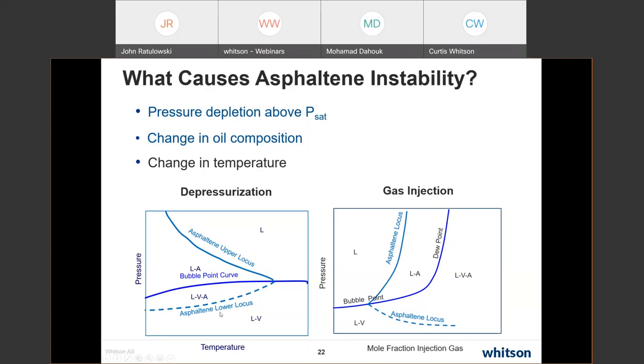Change in oil composition is specifically important in gas injection processes. You can see this phase diagram over here, which is similar to the sorts of phase diagrams we see with CO2 injection. You can see as I continue to add CO2 at some point here above the bubble point, I will have a region where I have the liquid phase, the oil phase, and asphaltenes precipitated. And again, as I go down below the bubble point, I'm releasing gas from the system. So I'm actually increasing the solubility of the asphaltene, and eventually it will go back in, maybe. So I have an area here of liquid, vapor and asphaltene, and a liquid vapor area over here.